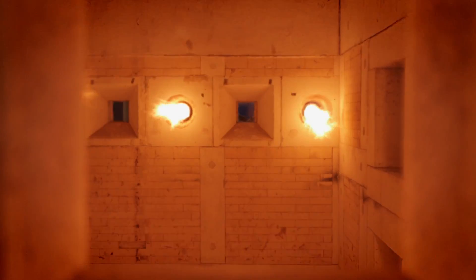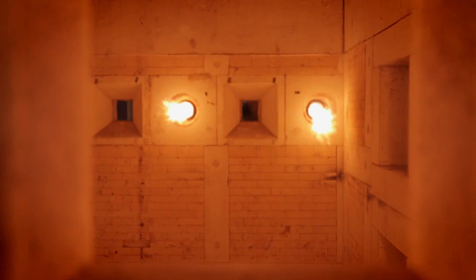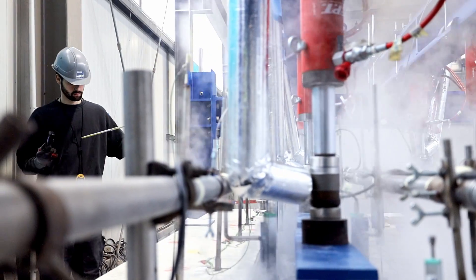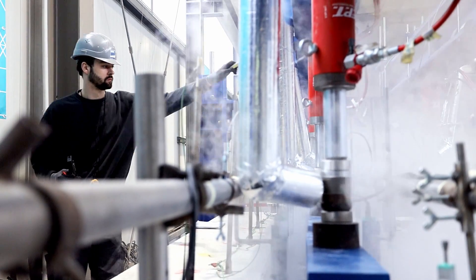The tremendous heat of more than 1,000 degrees Celsius during the fire exposure causes thermal cracking, an enormous increase in deflection of the structure, significant evaporation of moisture from the concrete, and superficial damage to the concrete from explosive spalling.